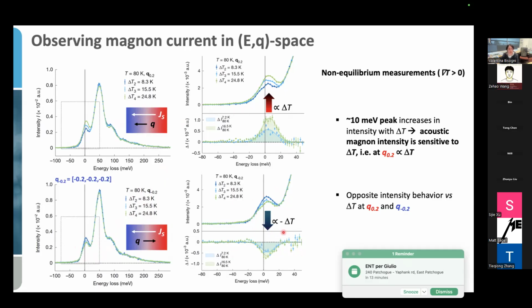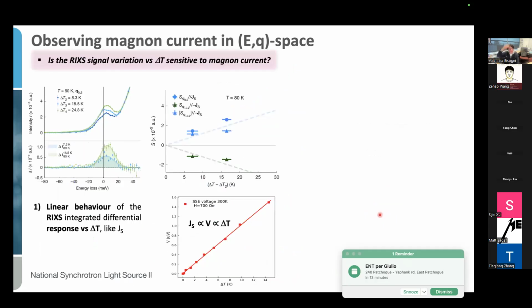So this is again zoomed in the central panel here. And the decrease in intensity again is peaked around 8-10 meV. But it has opposite behavior with respect to the positive Q. So now, how do we understand these responses that we see in RIXS as a function of the temperature gradient across our device? So can this be due then to the magnon current?